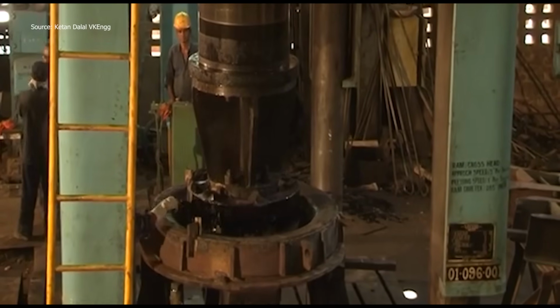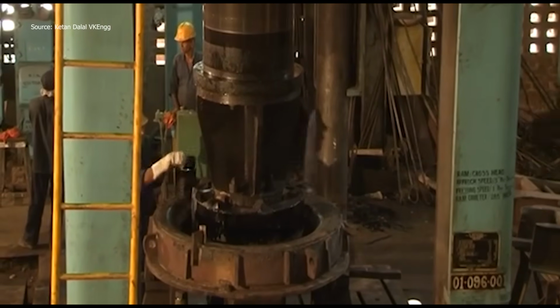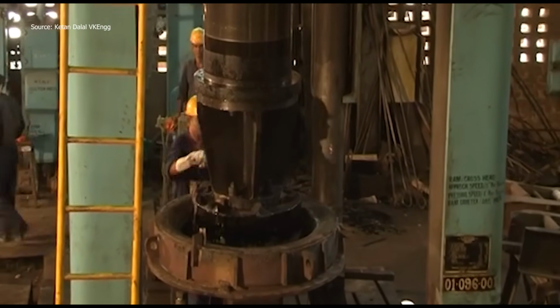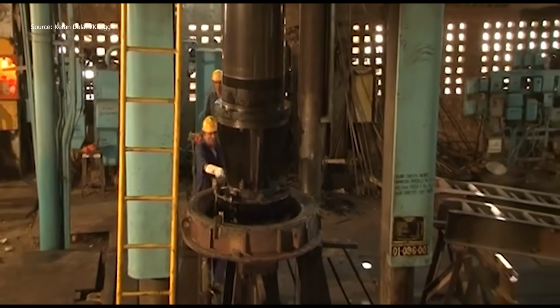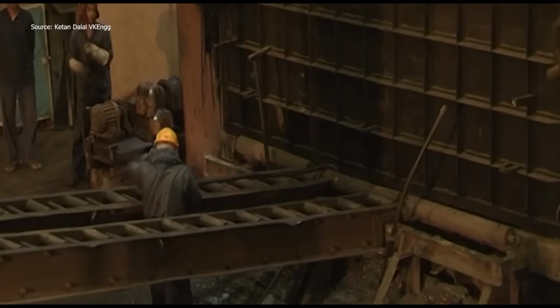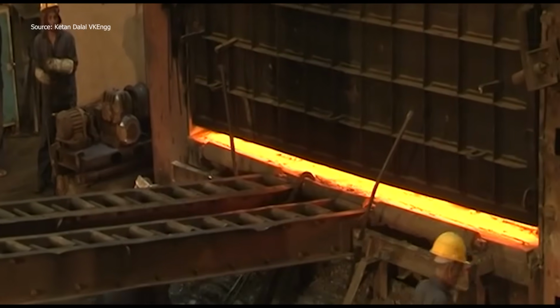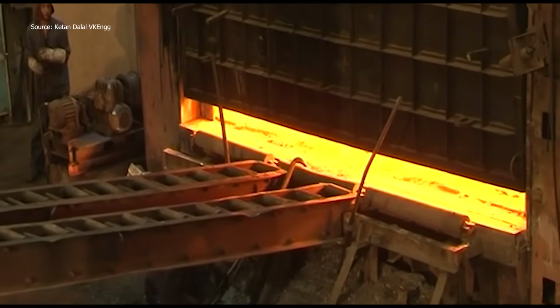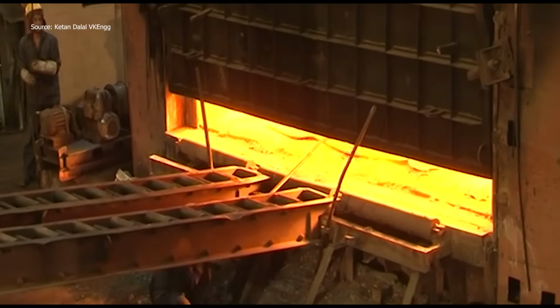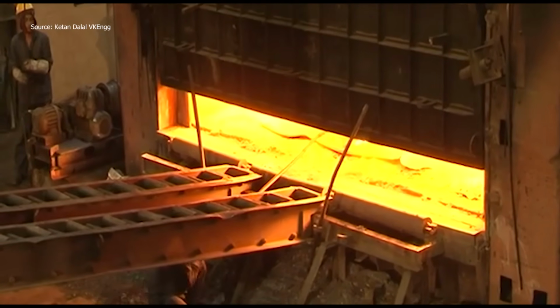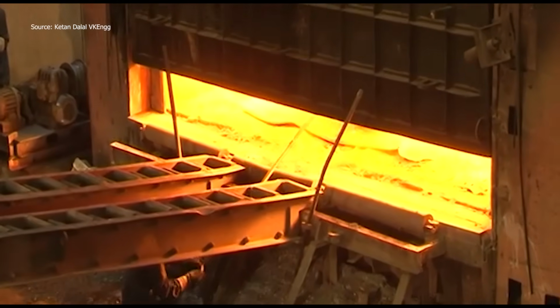Under massive pressure, flat steel transforms into a perfect curve, hydraulic forming at its finest. It starts with a flat steel plate, precisely cut to the desired diameter. The blank is placed onto a forming die inside the hydraulic press. From above, a matching punch descends, applying slow, even force.